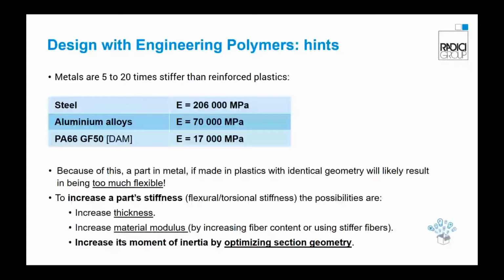In order to ensure the mechanical performance of the part, it is fundamental to increase the flexural and torsional stiffness, acting on these parameters. For example, increasing the thickness, increasing the material modulus by increasing the fiber content or using a different type of reinforcement, or increasing the moment of inertia by the optimization of the section geometry.